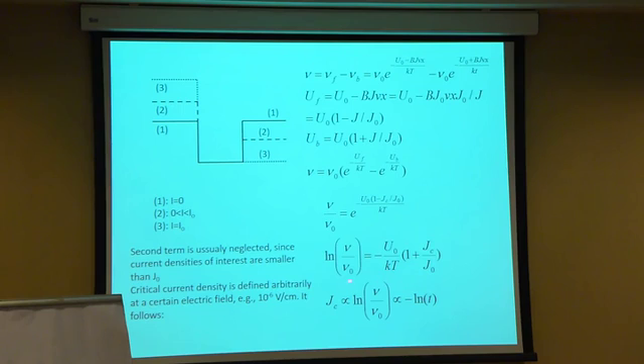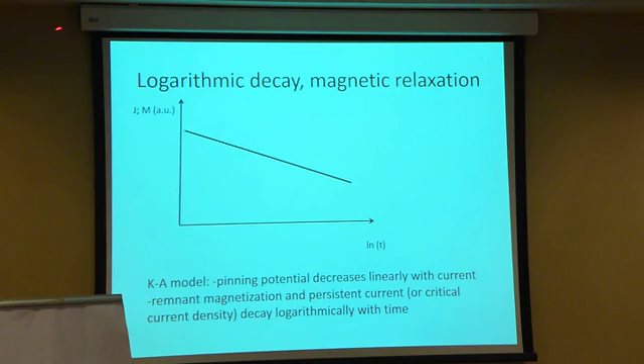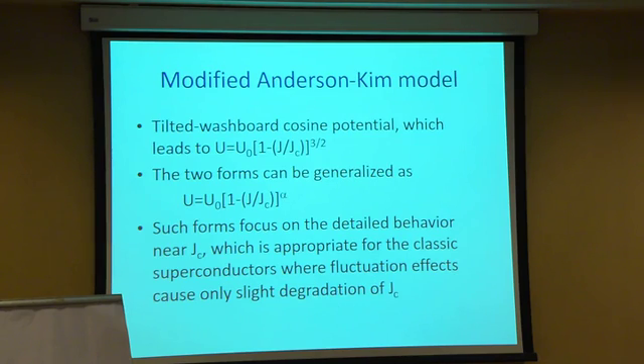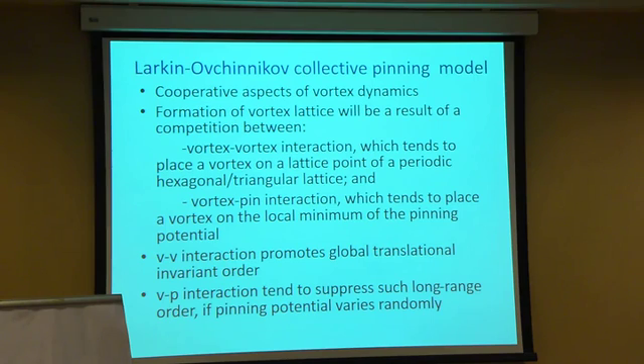So what happens is that Anderson and Kim predicted that critical current density will be proportional to the logarithm of time. And this is actually seen all the time in magnetic relaxation measurements, in which if you put in a circulating supercurrent, that current will decay logarithmically due to thermally activated flux creep. So this is what we have, logarithmic decay, magnetic relaxation. This is how the Kim-Anderson model predicts this kind of thing. Well, you can play a little bit with this one. I did that when I was doing my PhD. Doesn't matter, it's not very important.